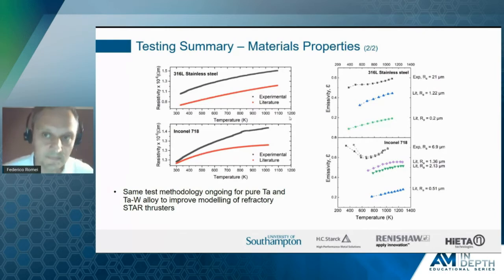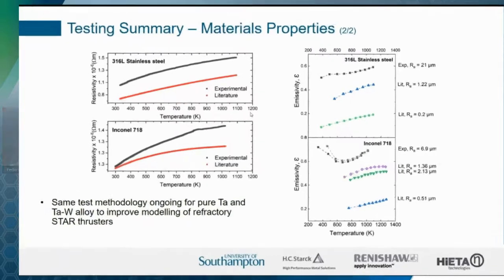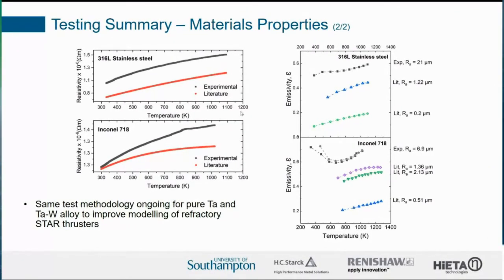So in summary, on the left here, you can see the resistivity that we experimentally measured in gray, and what we found in the literature for cast material, same material, in red. And you see that there is quite a difference, and this translated into very different results in the models. On the right, you see also the surface emissivity. And again, what we measured is relatively higher with respect to the cast material properties that we found in literature. And this is strictly related to the surface roughness.